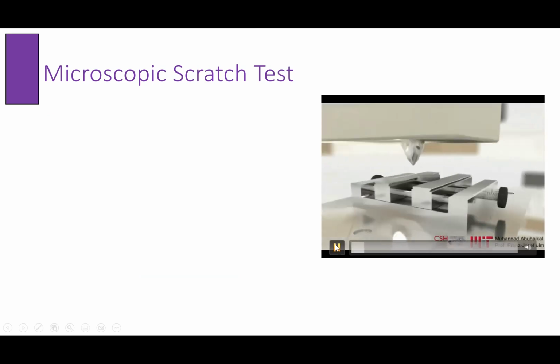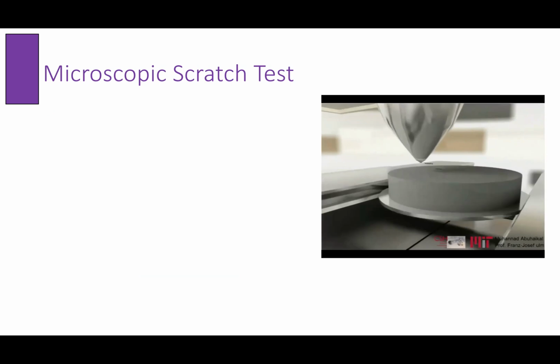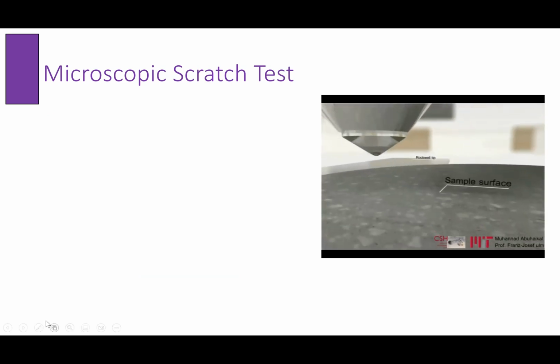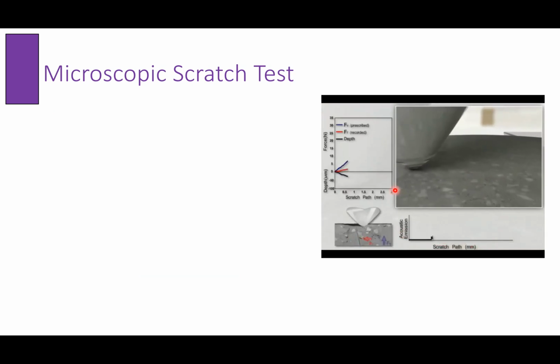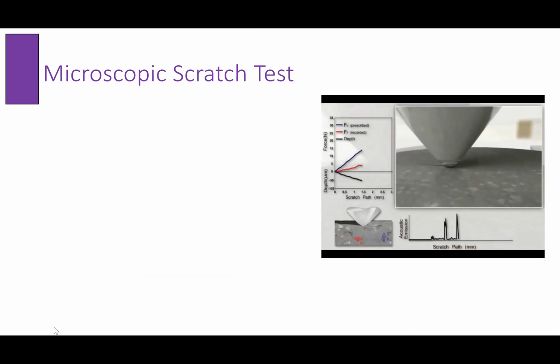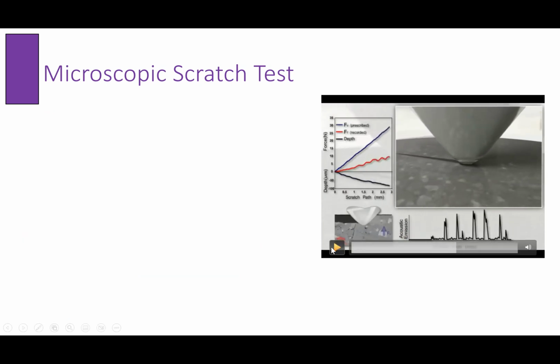So here's the principle of scratch testing. You're going to have a probe. In this case, you have a spheroconical probe, and you're going to push across the surface. What we are doing here, let me stop. We are prescribing the vertical force, and we are recording. So we prescribe the vertical force in blue, and we record the horizontal force in red and the penetration depth in black. And then you also have the acoustic emission that is showing peaks.